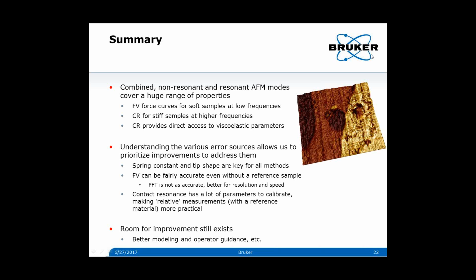Now the trick is, what frequency are you really talking about? When you're doing force curves, you could say, okay, I'm doing my force curves at 2 kilohertz, but should I really be comparing to DMA at 2 kilohertz? Probably not, because you're not in contact for a significant part of your force curve, and there are essentially multiple time domains being excited simultaneously, like harmonics in the sample. So it's a little less clear. You can look at the tip velocity, which can be measured from your force curves, and you could be more specific based on that.